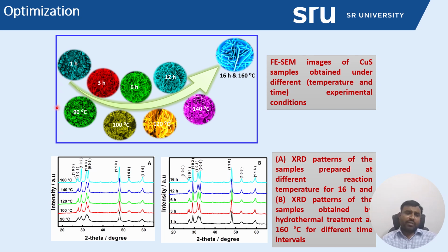Followed by, we have varied the temperature. Initially we used 90 degrees, which does not form any clear morphology; irregular particle morphology is observed. So it indicates that this low temperature of 90 degrees is not sufficient to form the perfect copper sulfide crystal structure. When increasing to 100 degrees, also there is no significant morphology. When increasing more, like 120, we can see some layered sheet-like morphology. At 140, about 70 percent flower-like morphology can be observed, but still it is not clear.